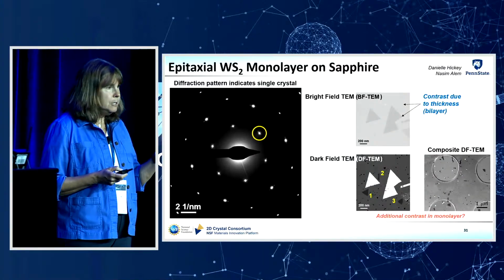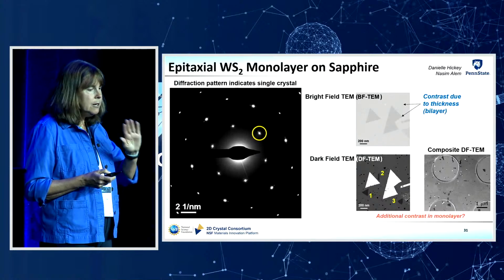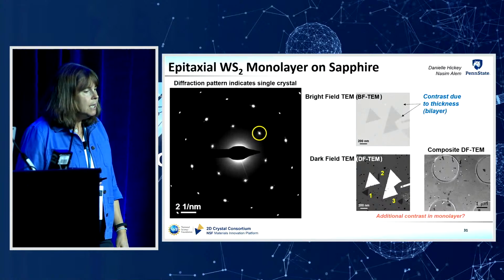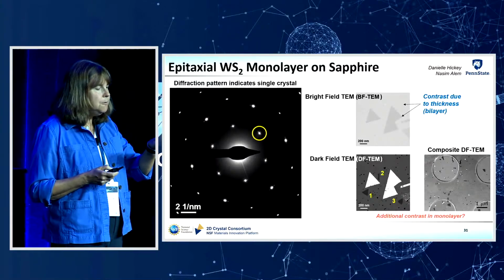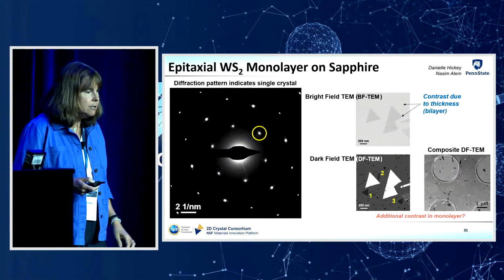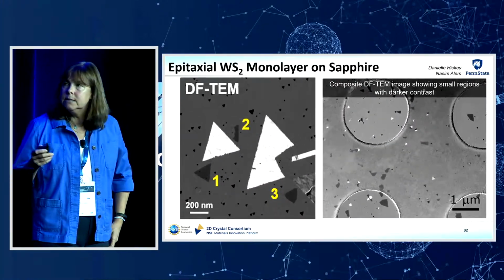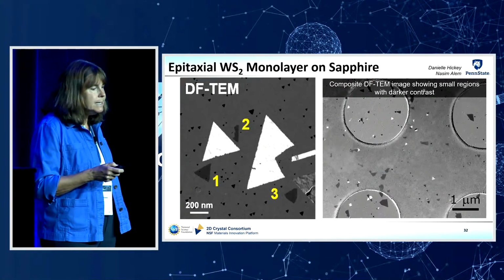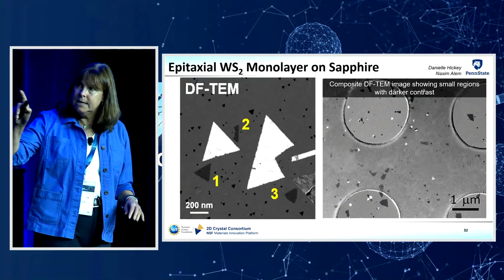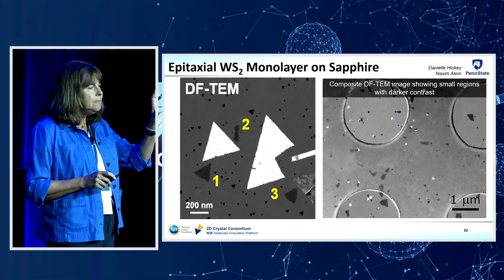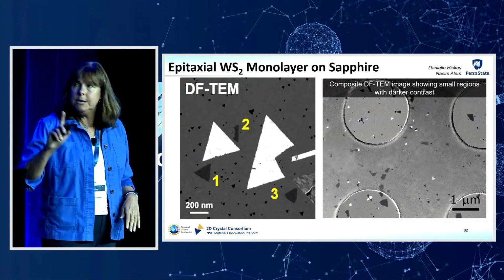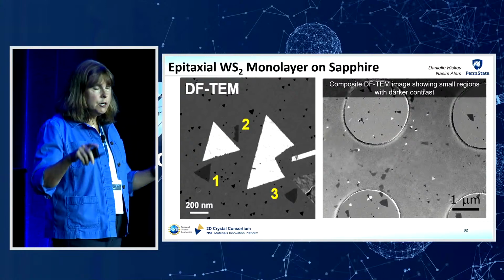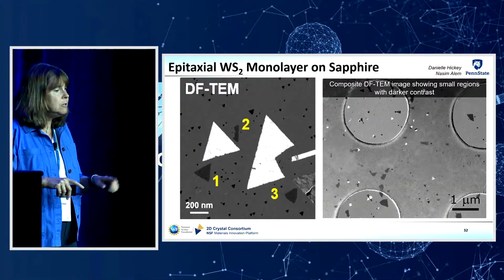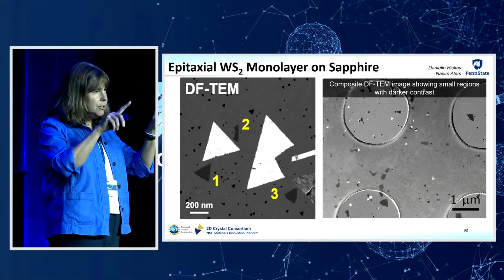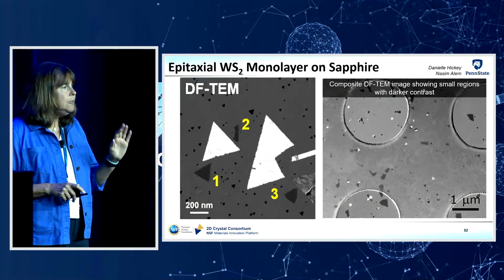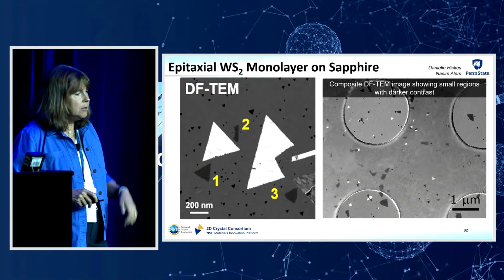But if we do dark field imaging, we can start to see contrast in the monolayer that we don't see in the bright field image. And I want to just point out a few features that I've marked 1, 2, and 3 in this particular image. So if we take a closer look at these TEM images, again, you can see these features. On the left side is just a single area, but if we take a number of these dark field images and we stitch them together, we can form a composite image of a larger area that's similar to the area of the AFM that I showed you earlier. And I should mention that these circular features that you see in the composite image, those are just artifacts from the TEM grid that this monolayer is sitting on.